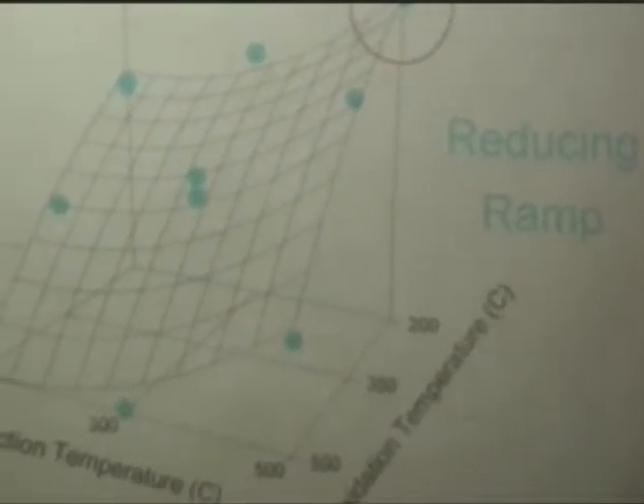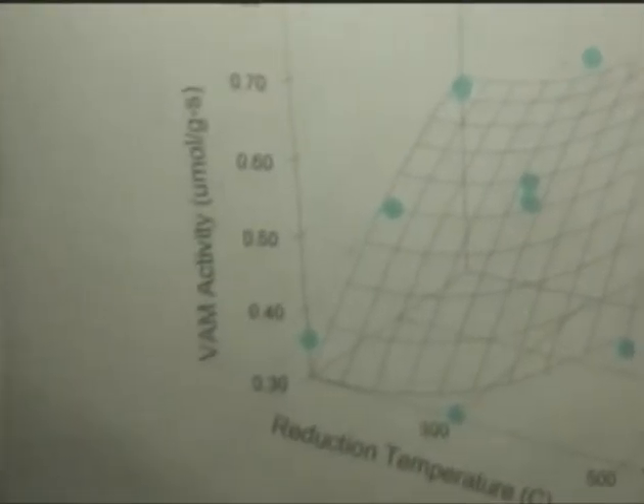If you look at these, somewhat cross-eyed, but for a little bit, you get a feel for the fact that if you have a reducing temperature that is at or below your oxidation temperature, there's no difference in whether you change that temperature as you ramp in an inert or you ramp in hydrogen. And you see that this side as well is fairly similar. The interesting thing happens when you reduce at a temperature higher than your oxidation.